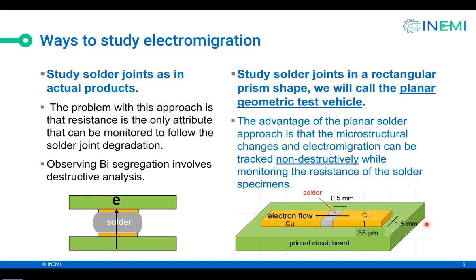Thanks, Haley and Rael. So let me get started. We have two ways of studying electromigration. The one shown on the left is using a BGA or bottom terminated component solder ball. In this approach, we can measure the resistance of the solder joint of the solder ball and thereby monitor the electromigration.